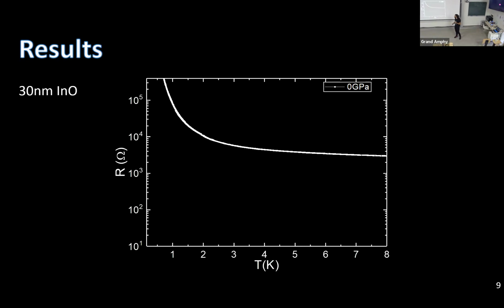We started with a 30 nanometer insulating indium oxide sample. We have here its resistance on a log scale as a function of temperature, measured at ambient pressure. We start with an insulating behavior, and we can tune the starting point of the indium oxide film with our evaporation chamber. And I can start pressurizing my thin film, applying pressure on our indium oxide.